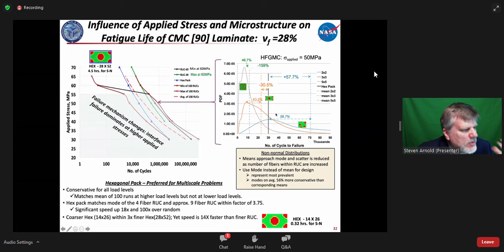And again, keeping with the spirit of understanding the difference between fidelity and speed and so forth, we've also thrown on here the analysis of the same load levels, but this is an ordered system with a hexagonal pack, and you see here that the hexagonal pack is significantly faster, obviously, because it's only one calculation, but it matches the average of the 100 RUCs reasonably well, and obviously it's also conservative. But it allows us to estimate life very reasonably, and we've also realized here that the hexagonal pack would be a preferred analysis for multi-scale problems due to its efficiency over trying to deal with the stochastic nature and having to run hundreds or thousands of full multi-scale problems with different microstructures.